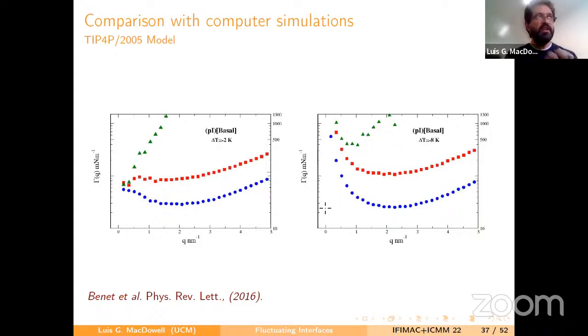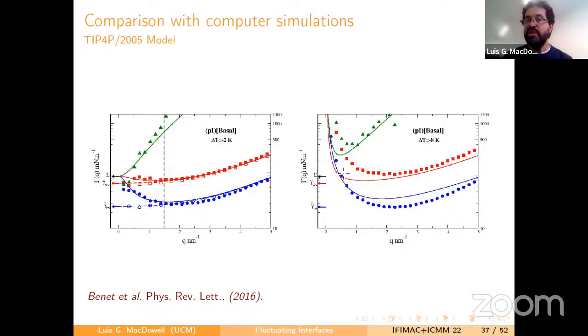We studied the fluctuations of the prism facet, that's the lateral sides of the hexagonal prisms, those are the prism facets. We studied their fluctuations, and very close to the melting point, just two degrees away from 0 degrees, we found that they all converge, and that is consistent with the scenario of an interface which is rough. But if we decrease the temperature just by 6 Kelvin, then we see that the fluctuations now are divergent, and it's consistent actually with the picture of smooth interfaces below the roughening transition.